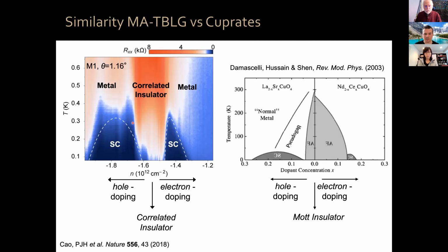Okay. Now, of course, an important difference between these two is that this is a theoretical phase diagram. Okay. In order to populate this diagram with actual experimental data points, you have to grow hundreds and hundreds of crystals with different chemical composition, different disorder, and often from different material classes, because not every material can be grown with the same, in different dopings. Okay. In this case here, this is all done in a single cool down with a single device, without the introduction of chemical impurities, and we can go from here to here in a few seconds. Okay. So that is one of the things that attracted a lot of attention. There are many similarities, also many differences between these two systems.